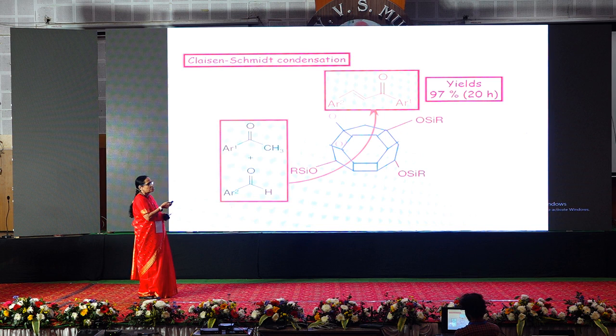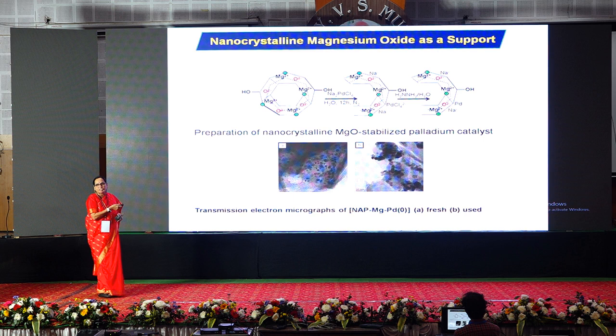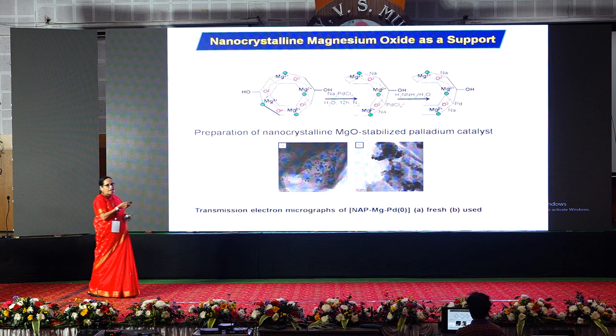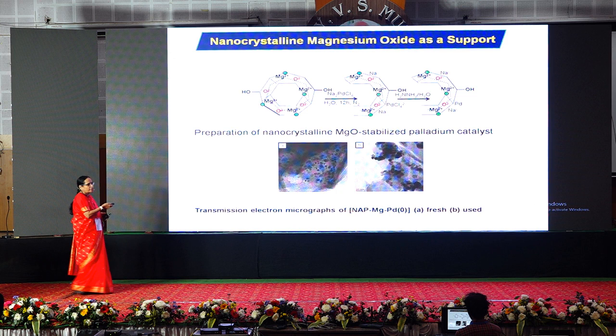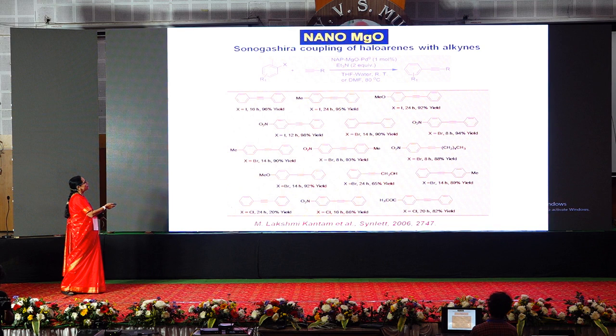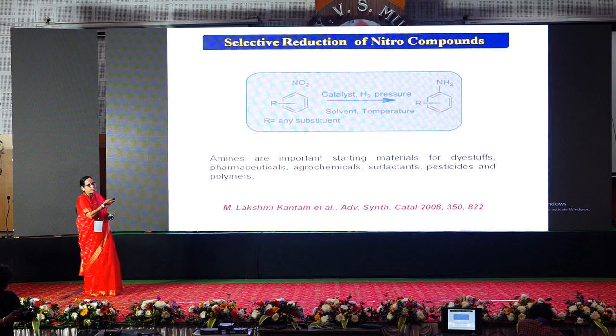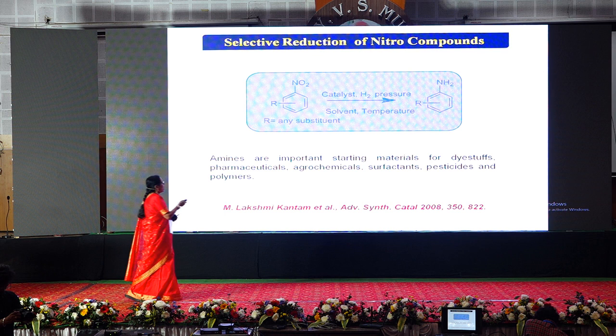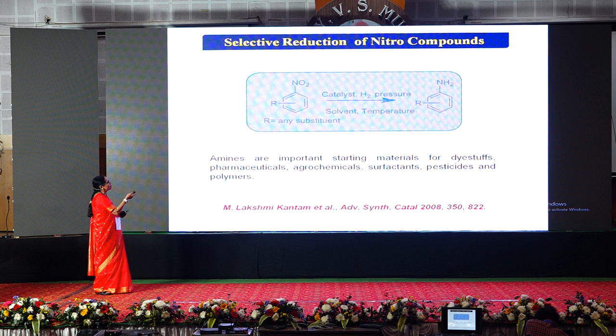And again, you can see the magnesium oxide can also be used as a support. Same like that, we put the palladium on hydrotalcite, we put palladium chloride, and then we reduced it and you will get the palladium zero on the magnesium oxide. And the important thing is, you can do any type of reactions. The important reaction we did is nitro reduction, which is very important. You want to make para-aminophenol. And you can see with this catalyst, just a hydrogen balloon, at room temperature you can do the reduction of the nitro compounds.